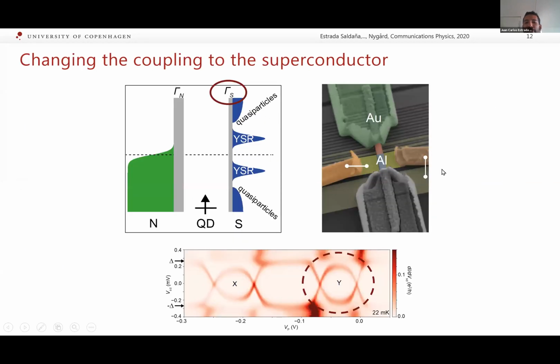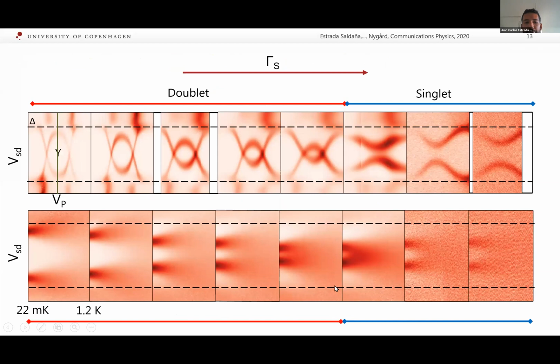So the first experiment that we did after correcting this is to see if these shifts depend on the coupling to the superconductor. So we're going to change the coupling of the quantum dot to the superconductor, this coupling gamma S, by changing this gate voltage, which is a gate located underneath the superconductor. And this gate is shorted to this side gate.